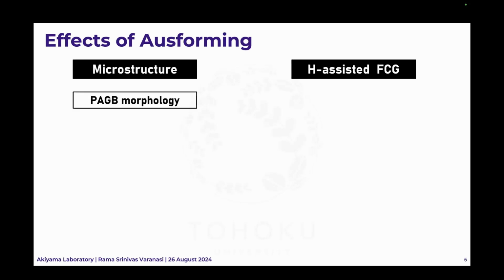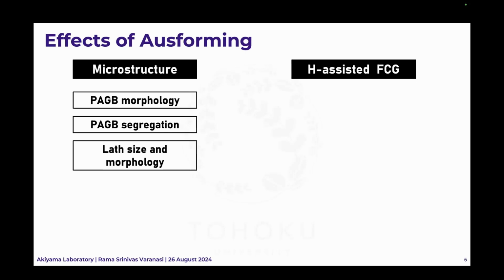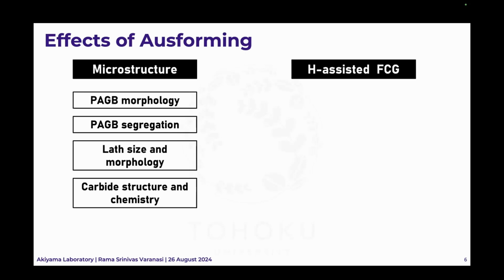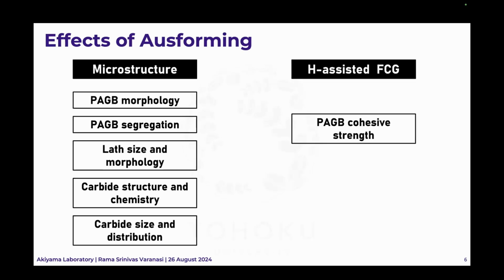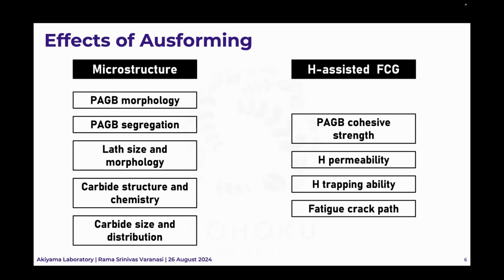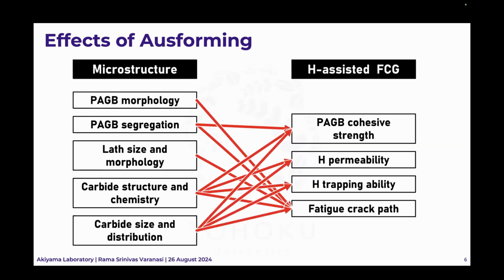In the microstructure, a few changes are the prior austenite grain boundary morphology and the prior austenite grain boundary segregation. We have the lath size and morphology, carbide structure and chemistry, carbide size and distribution. Now, these affect the prior austenite grain boundary cohesive strength, hydrogen permeability, hydrogen trapping ability, and fatigue crack path. So the PAGB morphology can directly influence the fatigue crack path. The prior austenite grain boundary segregation affects the fatigue crack path as well as the cohesive strength. The lath size, we expect it to affect the fatigue crack path. The carbide structure, chemistry, size, and distribution will affect all four components.